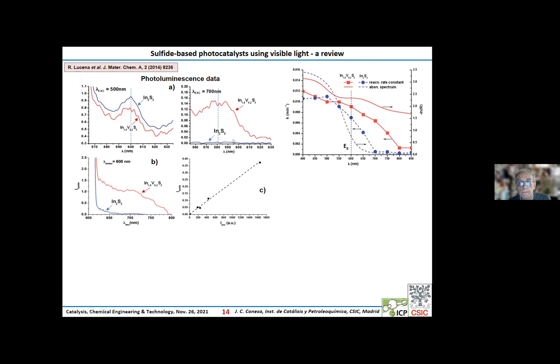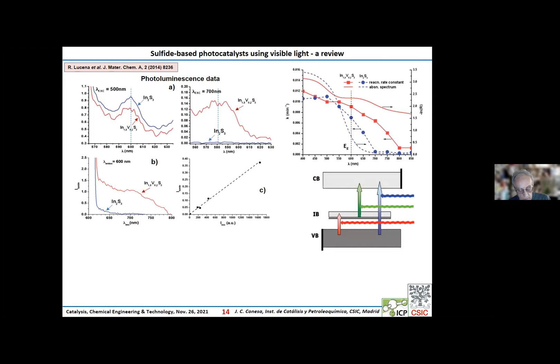As part A of the graph shows, and as part B shows, the extent to which the photoluminescence is extended coincides exactly with the extent to which the spectral response is extended, which means that holes can fulfill the photocatalytic degradation of formic acid. Part C shows that the photoluminescence intensity depends linearly, not quadratically, on the incident intensity, which means that both transitions can take place independently, agreeing again with the intermediate band scheme.